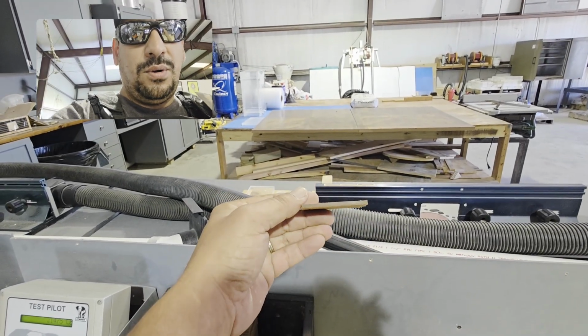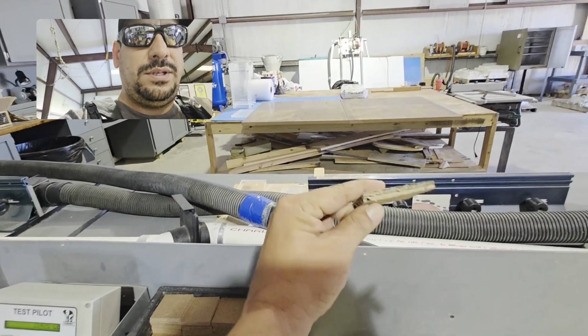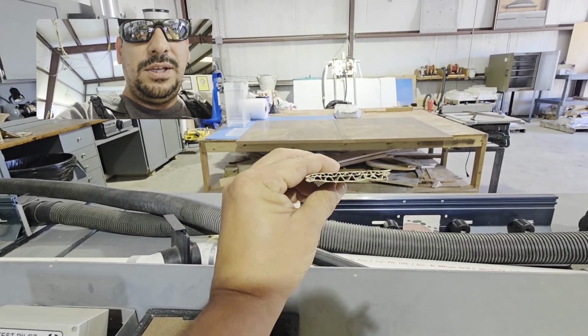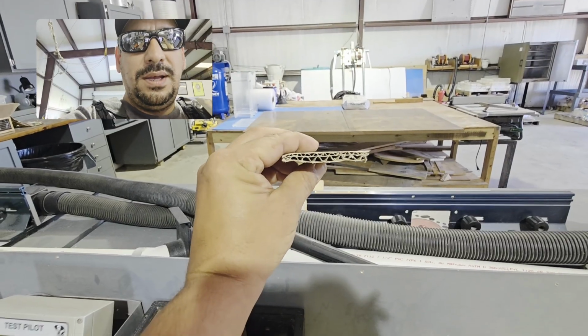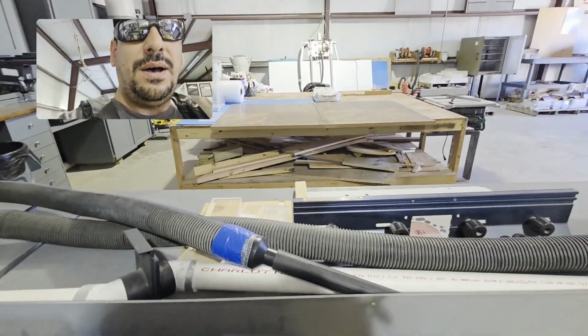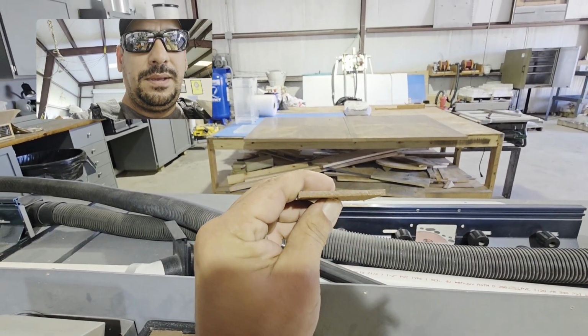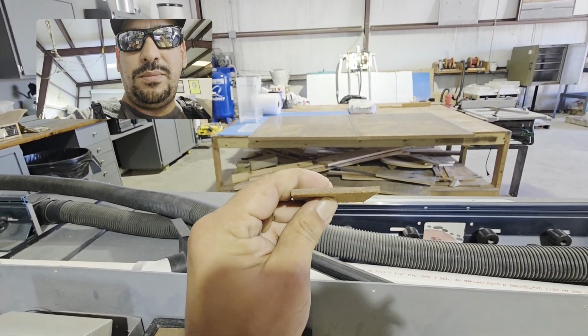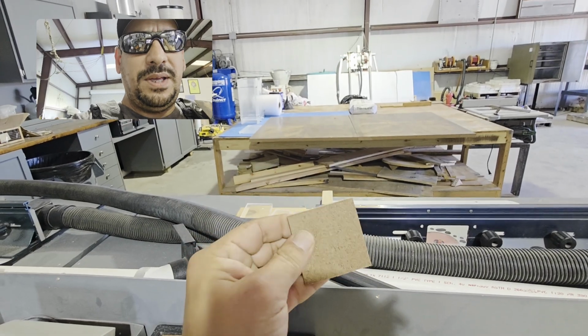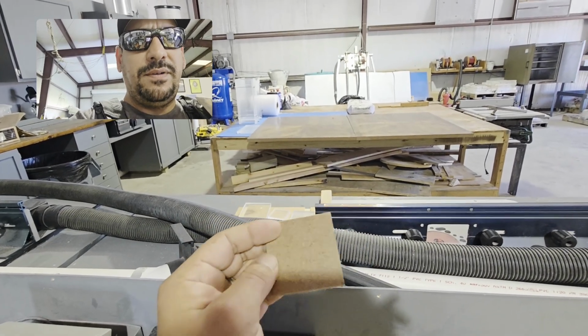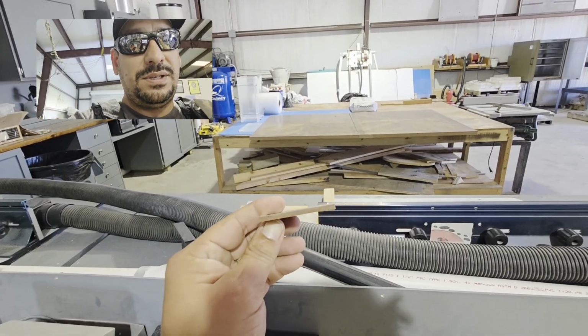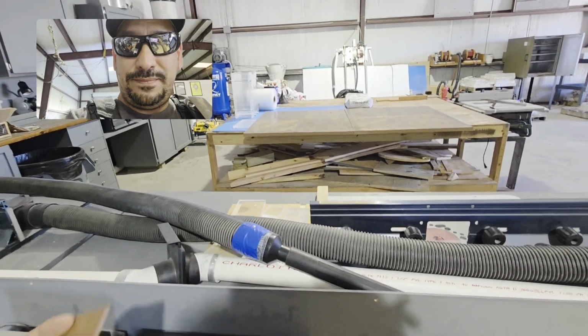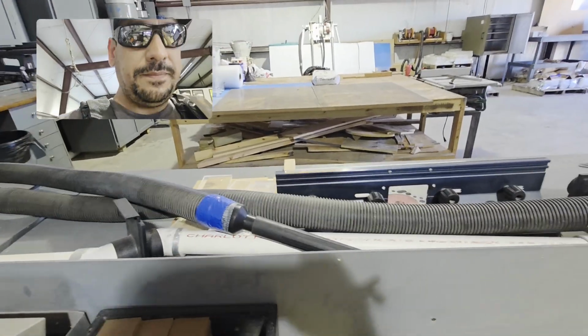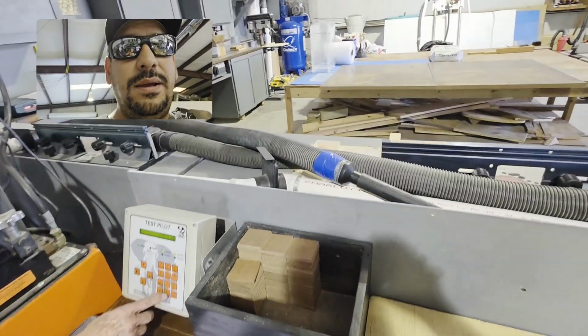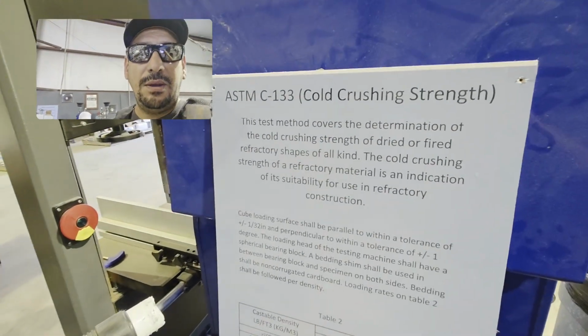They're non-corrugated, which means there are no corrugations in there. Like this one. This is a piece I cut out of a box. You can see that this one is corrugated. See all the corrugations that are in there? So they want you to use non-corrugated. So no corrugation. Solid cardboard, or they give you like an 1/8 inch paper type of shim. We always use these just because they give us better, more consistent numbers than those paper shims do. So remember that. Corrugated, non-corrugated for cold crushing strength, which again is the ASTM C133.